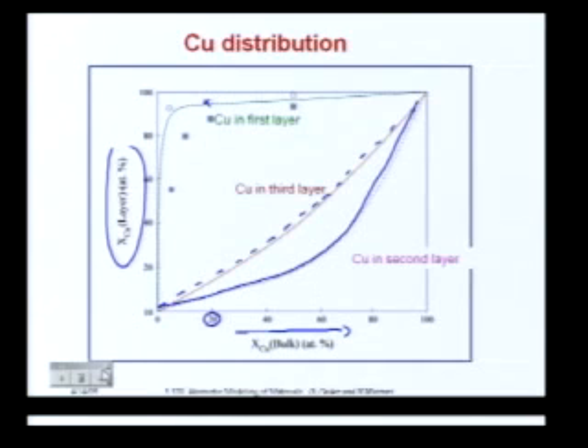First of all, why does copper go to the surface? It has a lower surface energy. So this is not rocket science. Most of the time, the thing with the lower surface energy goes to the surface. Okay? But why is it depleted in the second layer? Because I sort of think, well, if there's the lower surface energy, even in the second layer, it's sort of not perfectly bonded, so maybe it still wants to enhance its concentration there. But it actually depletes it. This is not atypical. It's very common in surface concentrations.